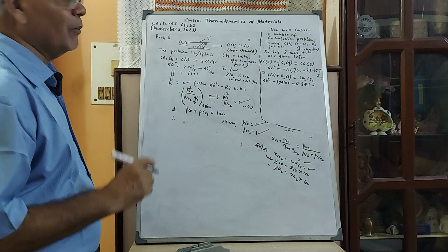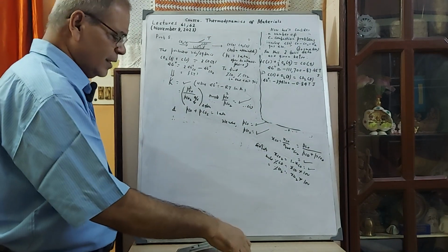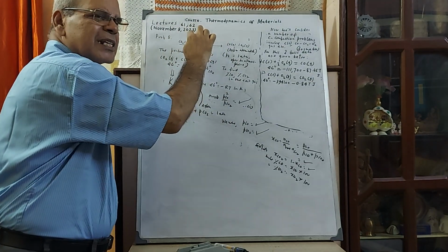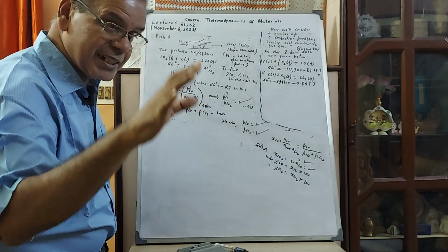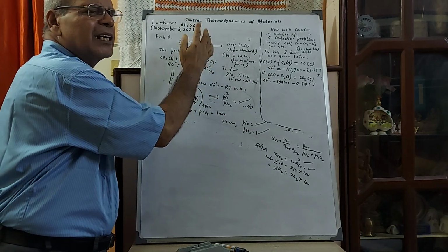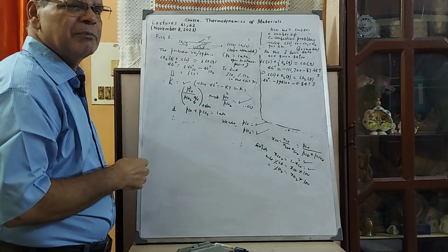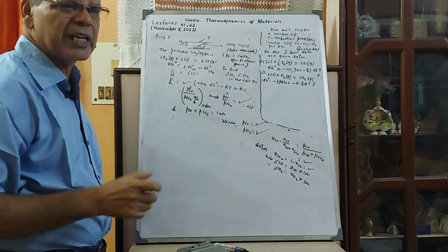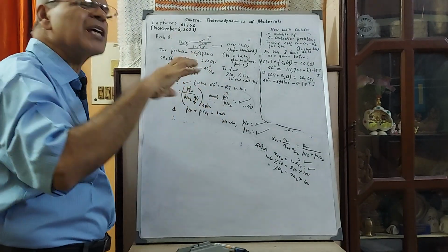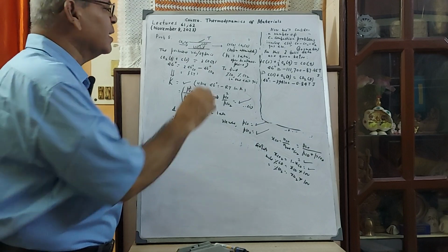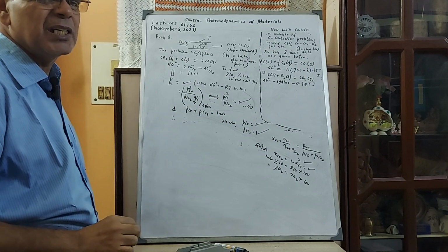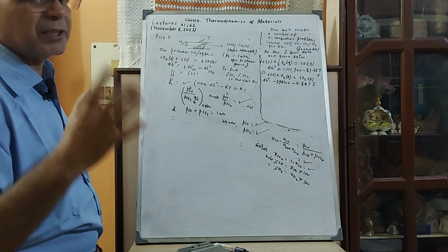So this is the outline. Okay, one thing. You follow this. When you follow the equilibrium, CO2 gas is traveling over carbon, and reaction takes place. It may be possible, if the reaction kinetics is fast and we are fortunate enough, that it will attain equilibrium maybe somewhere here, in the middle of the path, in the middle of the reactor. Suppose it attains equilibrium with fast kinetics. Kinetics has been favorable, and the gas is flowing slowly perhaps because you want slow passage, 20 cc per minute instead of 100 cc per minute.